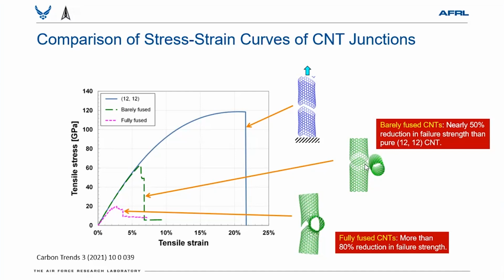And from a practical point of view, this makes sense because from a processing point of view, it's also easier to fabricate because you just lay carbon nanotubes on top of each other, then do heat treatment. That would create a welded junction, versus creating this kind of junction is more tedious because that requires more process control and also computation from doping and so forth. So this computation gives guidance to processing engineers on how to design this kind of junction. And this, we are the first to show that overlap junction creation is much easier and also, from a strength point of view, robust as compared to fully fused junction.